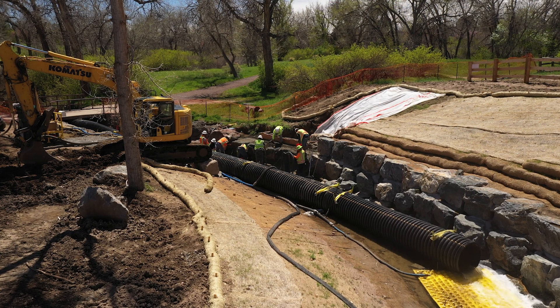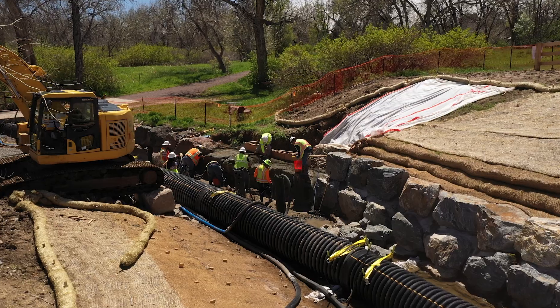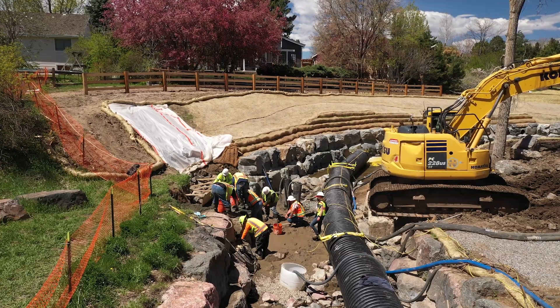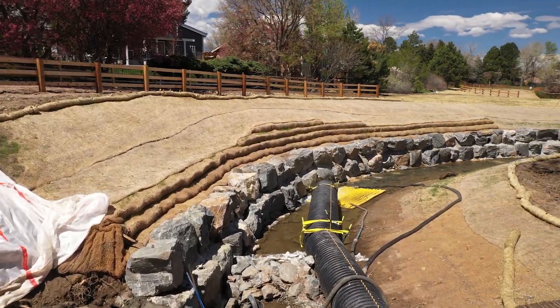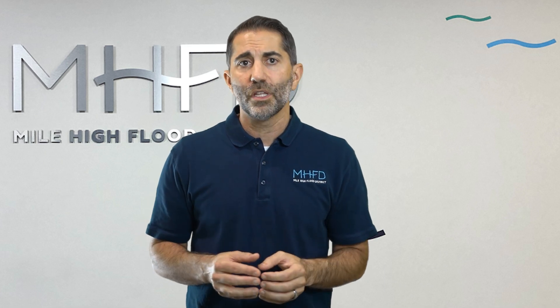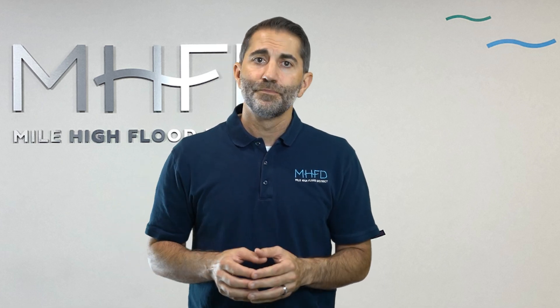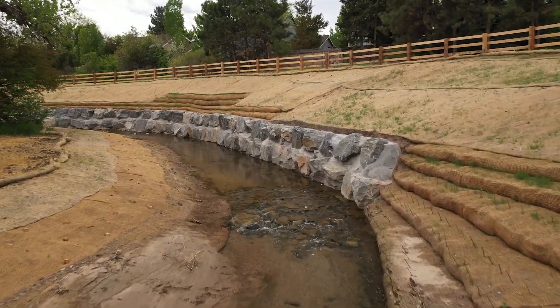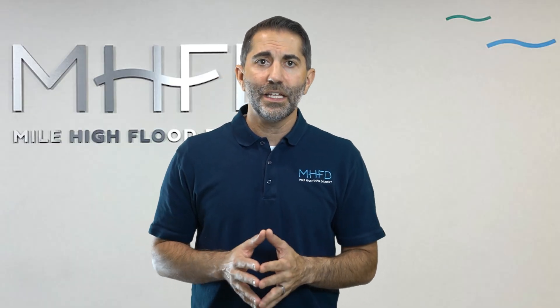In wall applications, boulders can be placed in single rows or stacked in two rows. To ensure a firm ground foundation, the bottom row of boulders are usually placed on a layer of small riprap. Boulder walls are considered gravity walls that rely on the weight of the boulders to hold them in place and resist lateral pressures exerted by the retained soil. Careful selection and placement of the boulders is required to ensure stability during stacking. After boulders are placed, grout is poured behind the boulders. During grouting operations, it's important to fill all the voids between the boulders while preventing the grout from spilling out in front. This is why grout for boulder walls is typically placed in lifts. Keeping grout recessed from the wall face a distance of about a third the boulder diameter provides an attractive dry-stacked appearance. Keyways and other cold joint details are needed anytime grout is placed in lifts.